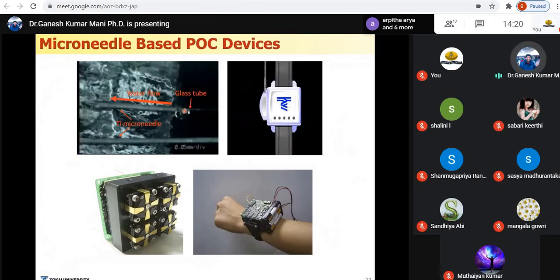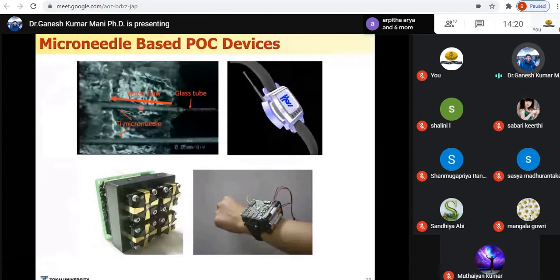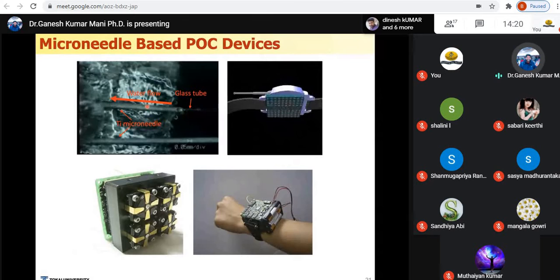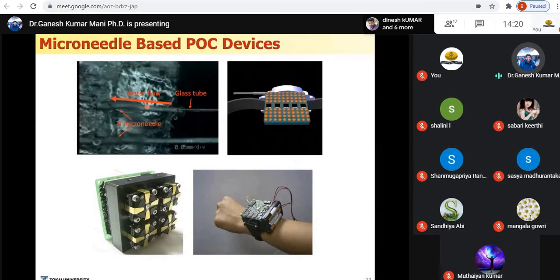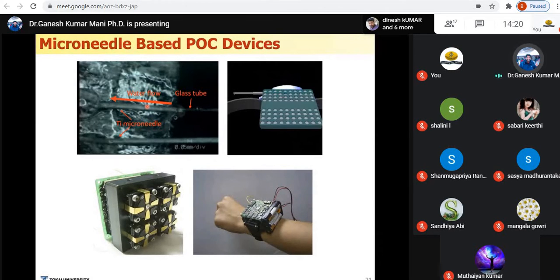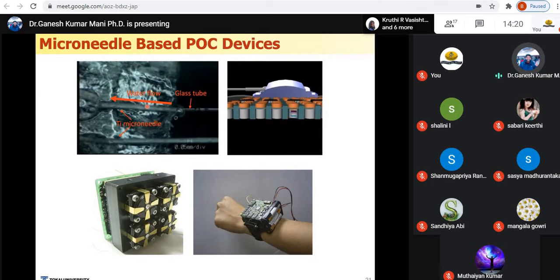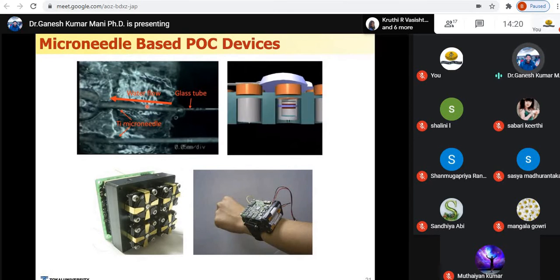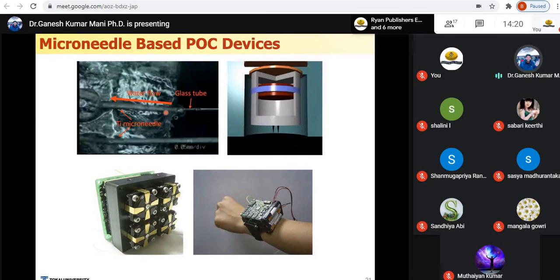As a first step, we confirmed the pain evaluation. As a second step, we wanted to confirm its hollowness. So we inserted a micrometer-level glass tube into this artificial titanium microneedle, and we passed water. You can see the water coming out on the other end. So it confirmed that the complete structure is hollow and unbroken, because you can see there is no leak. Using this microneedle, we developed a wristwatch type device for glucose sensing.